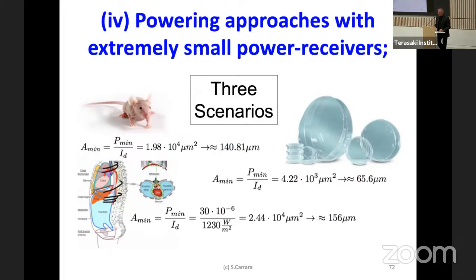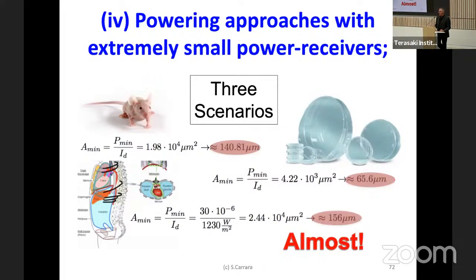Translational medicine, where the mouse is small, so the electronics will be close to the surface of the transmitting station. Or in vitro diagnostics, where we can mix the electronics with our sample and then put the plate on a powering device. Or, for example, heart monitoring, where the organ is so close to the skin that you are not very deep in the body. Well, in those cases, you see a decent amount of power in a few microwatts. A few microwatts power scale seems not to be that big, 150 down to 65 microns.